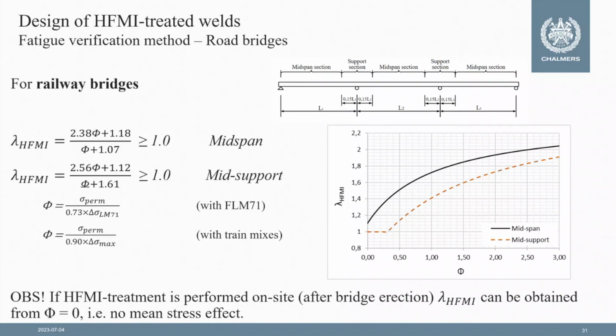Of course, if we have a situation in which HFMI is performed when the bridge is erected and the permanent load stresses are in place, then phi equal to 0 can be used, and the value of lambda HFMI would be very small. Otherwise, we will end up with a higher lambda HFMI, which will reduce, let's say, the benefit of HFMI to some degree, depending on this factor phi in principle.